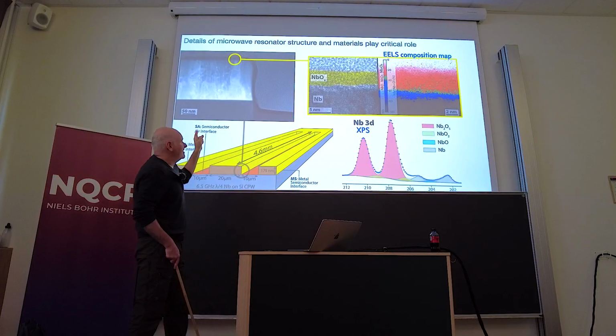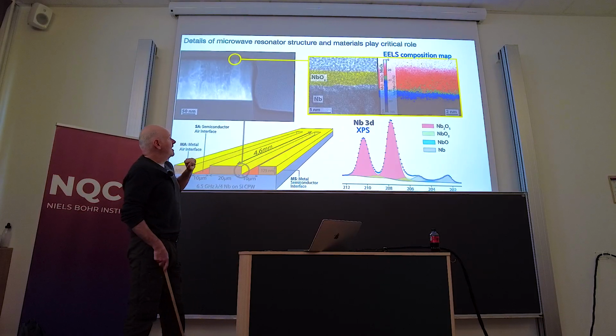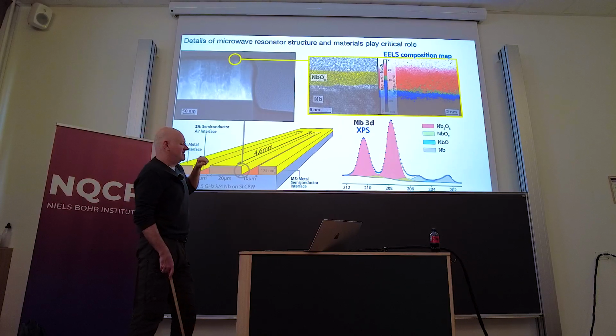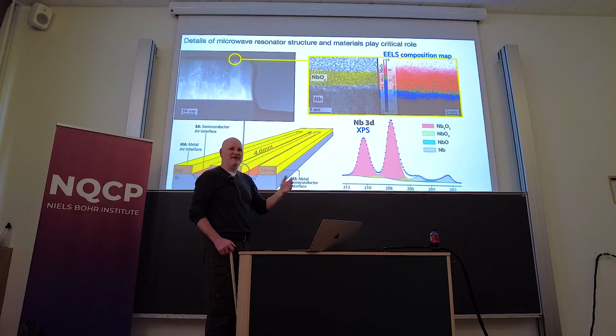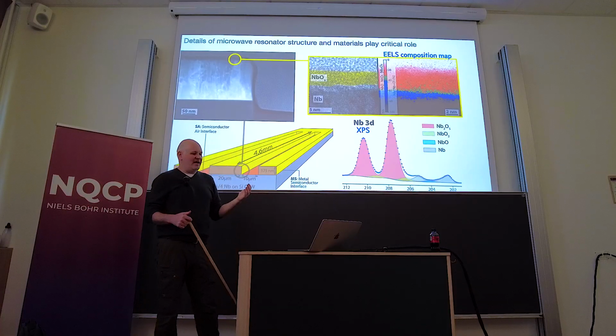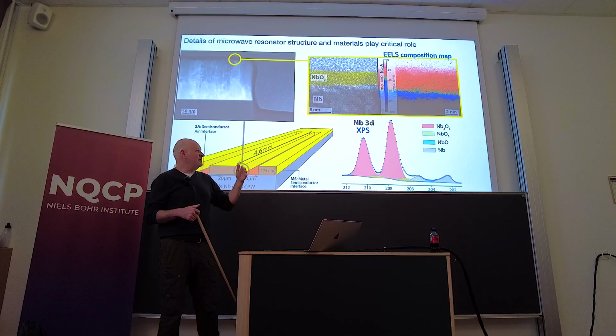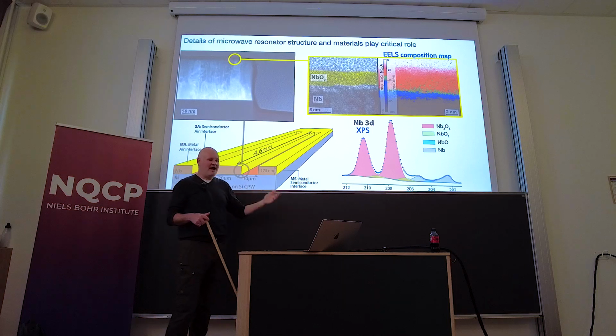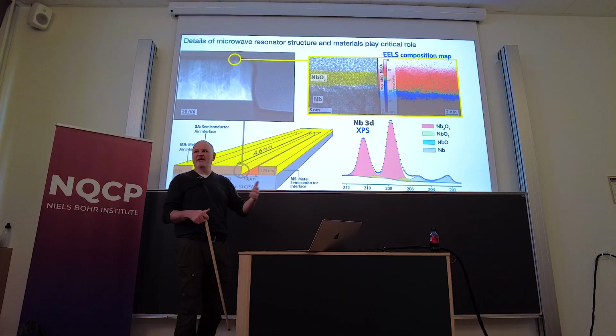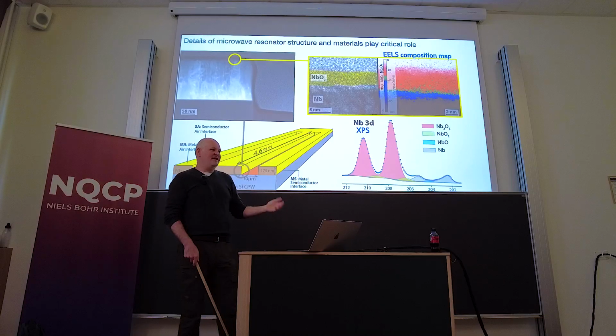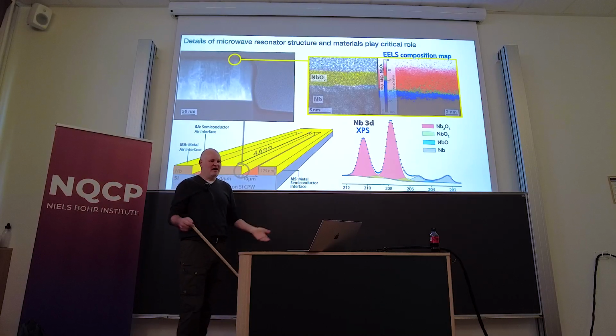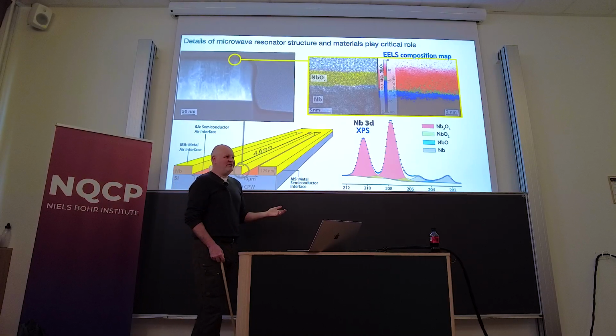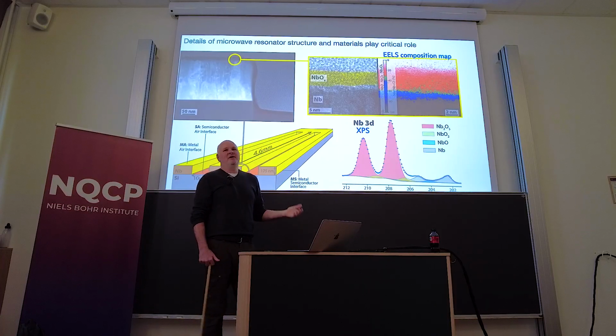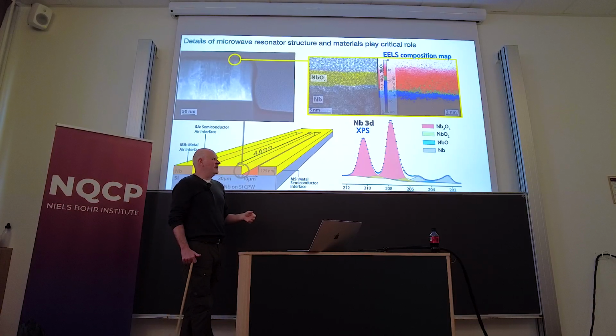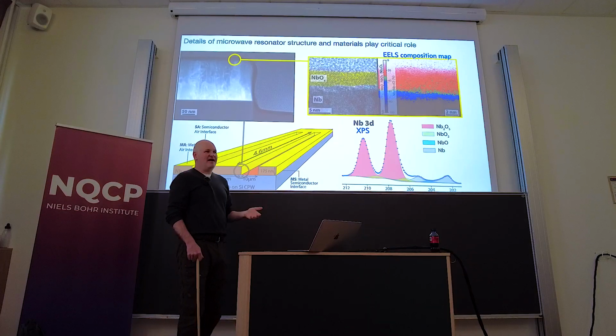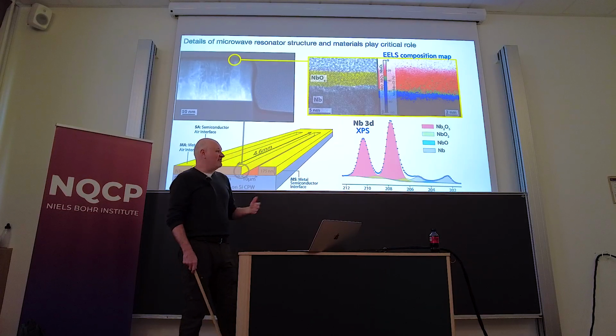However, at the niobium, this is where the problem really starts. On the surface of the niobium, because the thing to keep in mind about the fabrication for all these is that you start with essentially a material, your niobium, that you've put down, and depending on how you do it, you always end up with some kind of resist that's covering everything. And you need to remove the resist and all the residue and all the process gunk that appears. And so the standard way that you deal with this is you put it into an oxygen plasma, which works very well for removing carbon, but it also works really well at oxidizing niobium and silicon and everything else.